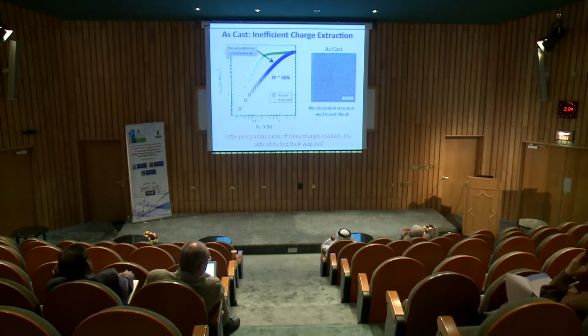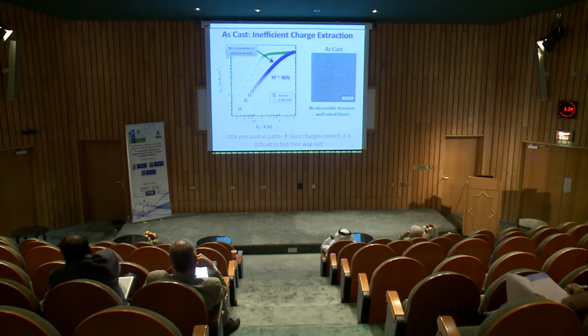The first one I wanted to look at is the As Cast device, the blue curve. I showed you earlier the fill factor at about 40%. And you can see that as you increase the effective bias, you continue to generate more and more photocurrent. So we never see the saturation current in the device. So what does it mean and how is it correlated to the morphology? It means that in this device, you can have very high photocurrent. You have no problem generating the charge carrier. But the issue here is charge extraction.